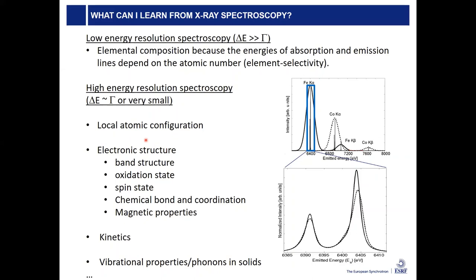What can you do? You can see the local atomic configuration with this technique. You learn about the electronic structure, band structure, for example. You can learn about oxidation and spin states. You can characterize the chemical bond. You can identify your local coordination, the ligands, interatomic distances, bond angles, if possible. And you can learn about magnetic properties. There are techniques, in particular X-ray magnetic circular dichroism, that tell you about magnetic properties of your sample. So this is also possible.